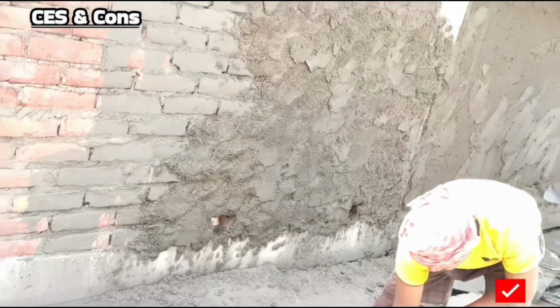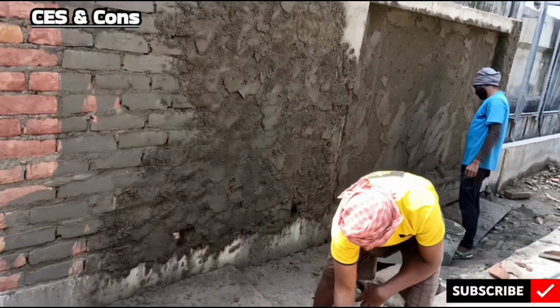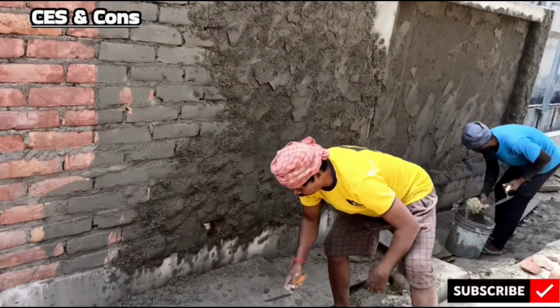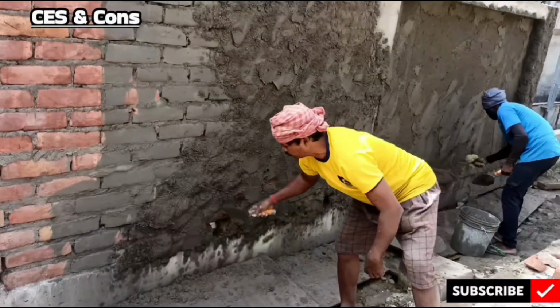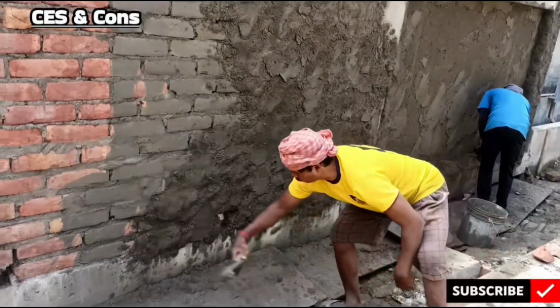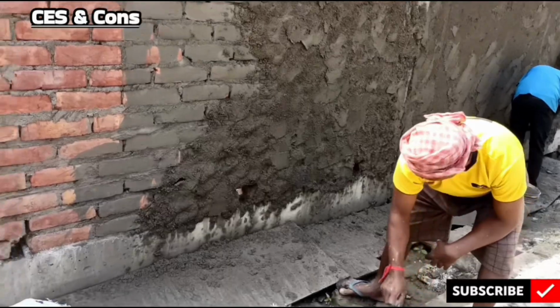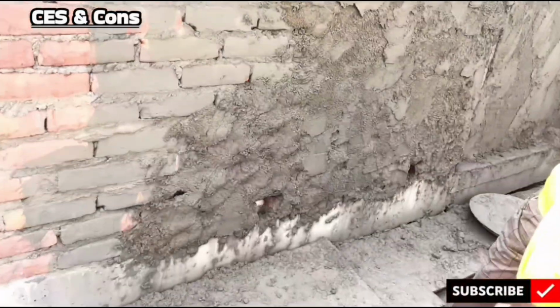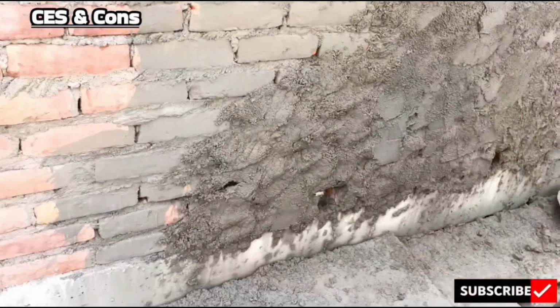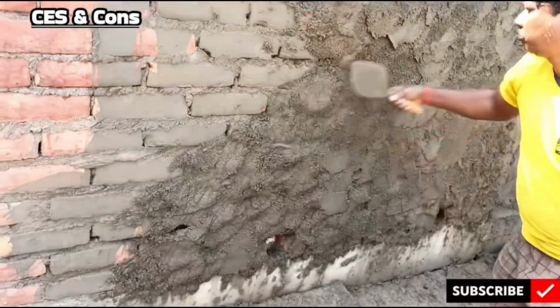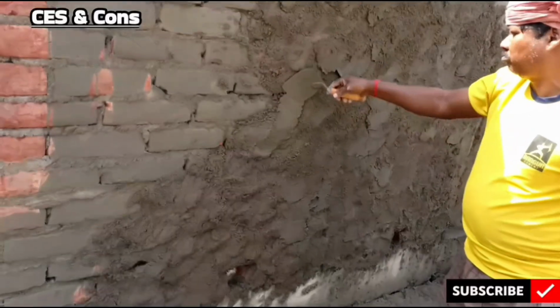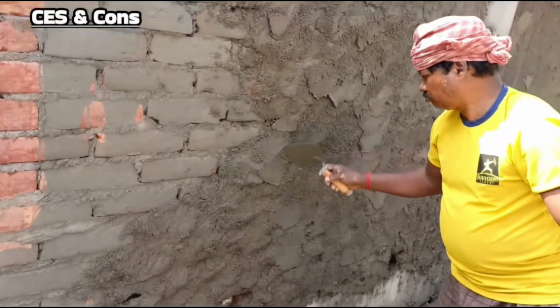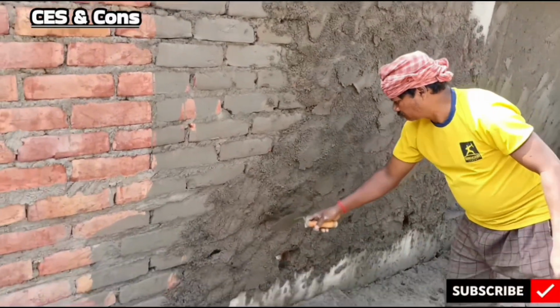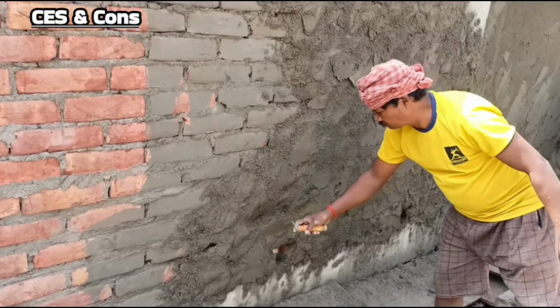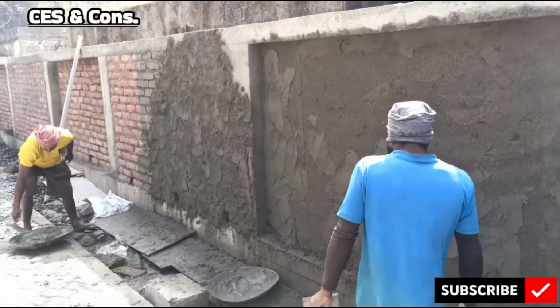Mortar mix proportion for plastering work. The cement sand proportion depends on the type of plaster. For internal walls, it is generally 1:4 to 1:6 proportion. For external walls, a richer mix like 1:3 or 1:4 is used for better durability. For ceiling plaster, 1:3 is common. The thickness should be in accordance with IS 2402-1963, Code of Practice for External Renderings and Finishes.